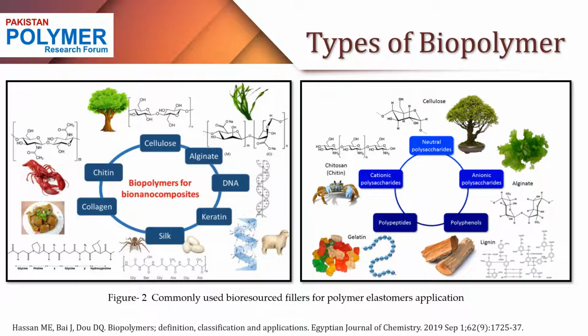But the major disadvantage of biopolymers, irrespective of their large number of advantages, is that they are hydrophilic in nature, while polymers are intrinsically hydrophobic. Because of this hydrophilicity and hydrophobicity, the compatibilization of these bio-based polymers with elastomers is tricky and a major point of discussion. But this issue could be minimized by surface treatment of biopolymers with certain specific chemicals that can improve the compatibility of bio-based polymers with the elastomers.